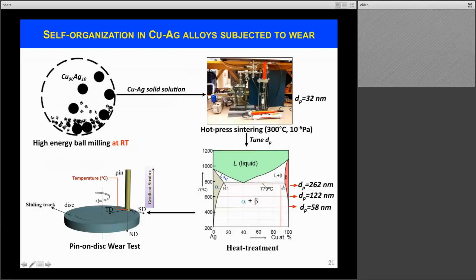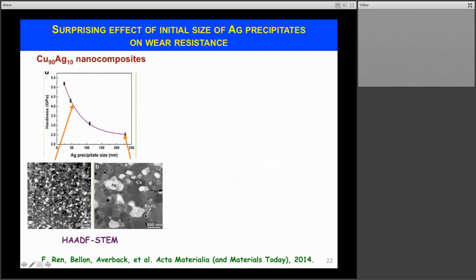So staying again with this copper-silver system, we ball mill, we make powders, we compact the powders and sinter them at intermediate temperature. And then we tune the size of the silver precipitate by annealing at different temperatures. In this particular case, we have a prepared copper-silver composite with here 10% silver and copper, with precipitate sizes ranging from about 30 nanometers to about 300 nanometers. And then we use a pin-on-disc test to see how this copper-silver composite performed for different precipitate sizes.